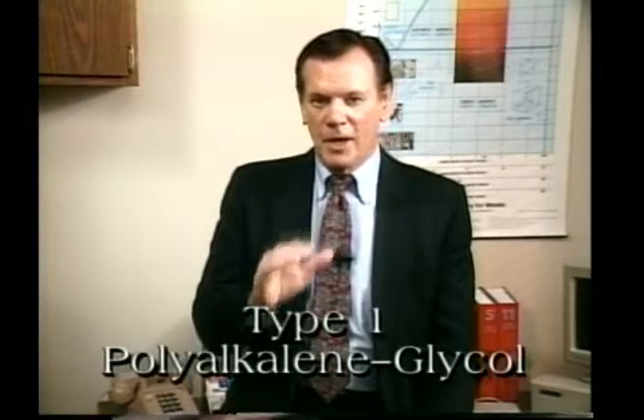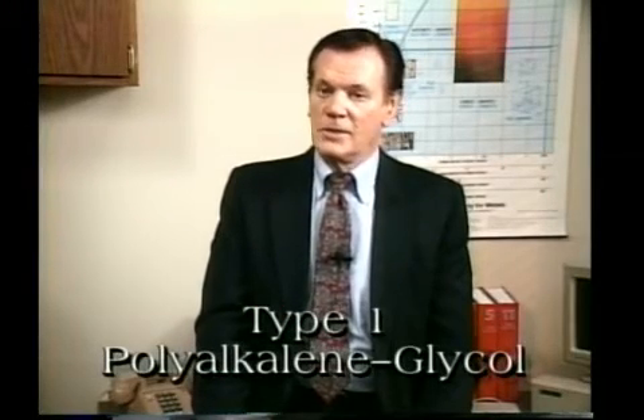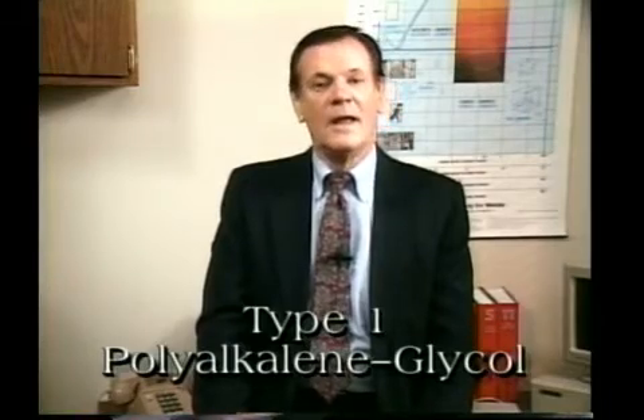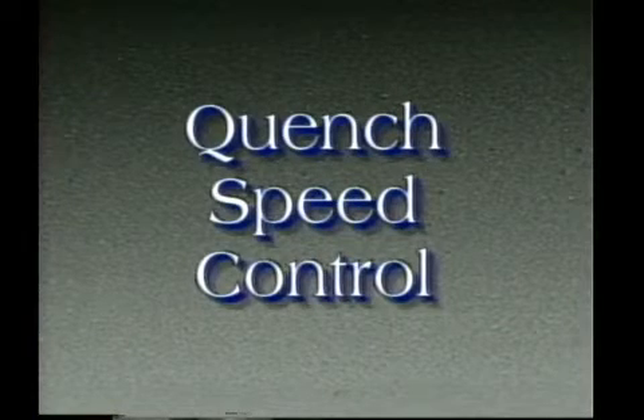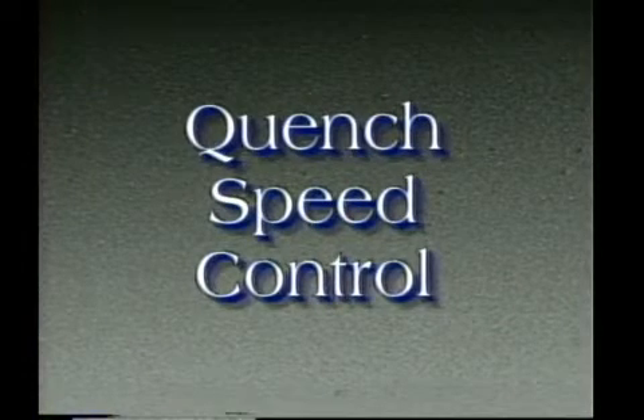The most accepted of the available polymer quenchants is the Type 1 polyalkylene glycol-based quenchant, which is specified in the SAE specification AMS 3025. The speed of the polymer quench is controlled by varying the concentration of the polymer. Heating the tank is not necessary. The higher the concentration of the polymer, which is water-soluble, the slower the cooling rate. Slight temperature changes in the tank do not significantly affect the cooling rate. Thus, the problem of obtaining different quench rates due to the temperature variation, which commonly occurs in a hot water tank, is not a factor.